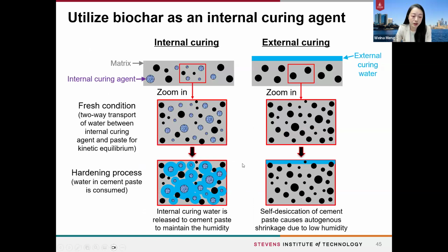What we did is pre-saturate the biochar in water for 24 hours to make it saturated surface dry. With this water, it works as a reservoir and absorbs some water inside. When we put it into the cementitious system, it will hold the water during the mixing and release the water during the hardening process. Compared with external curing strategies, especially for very dense types of concrete, it can provide much more effective curing for the concrete.